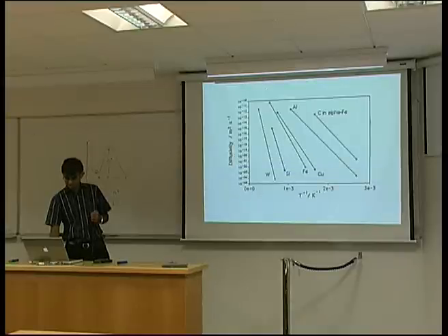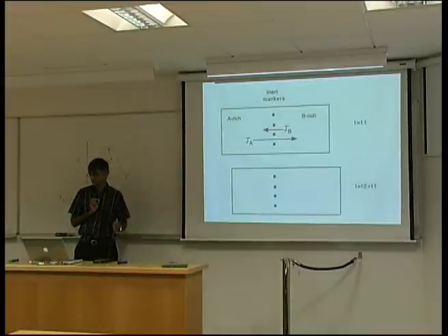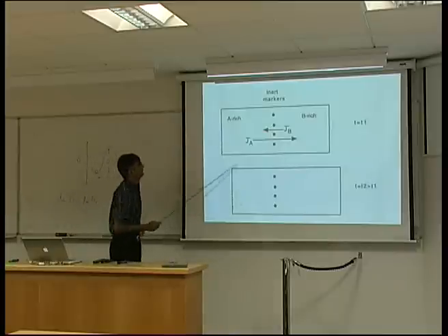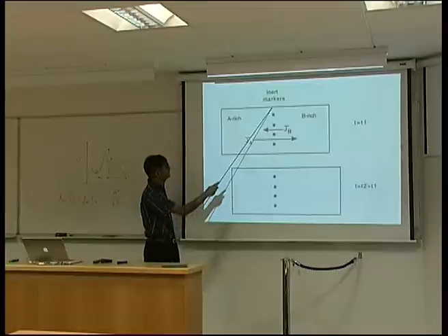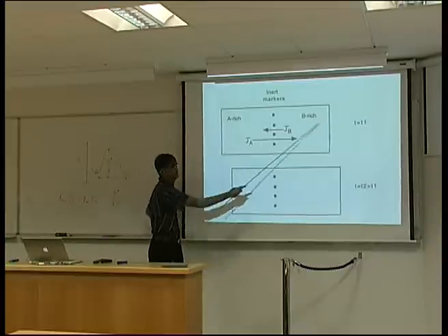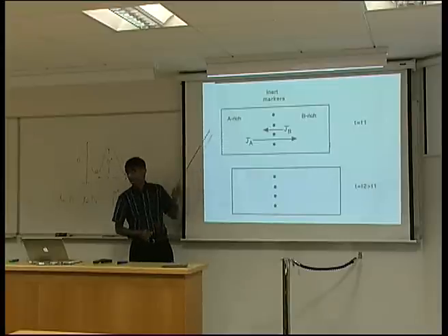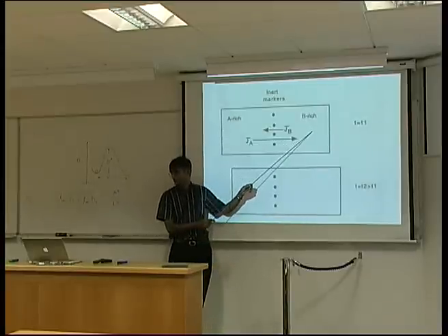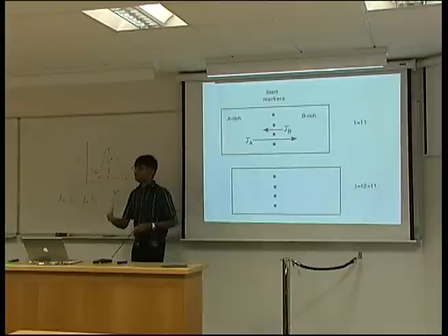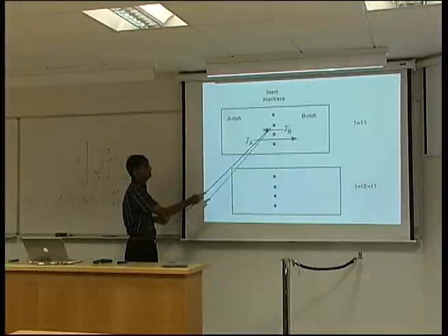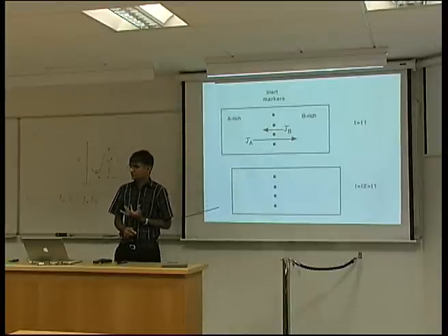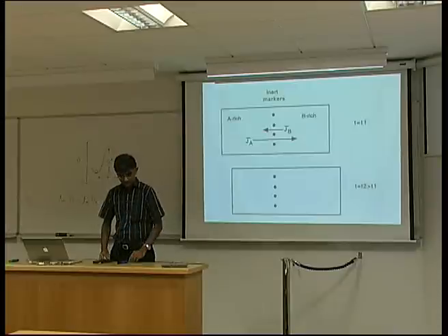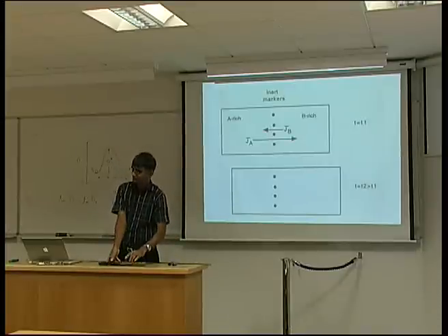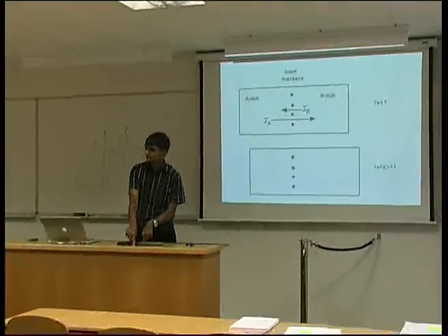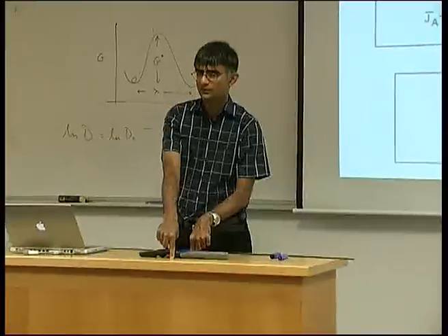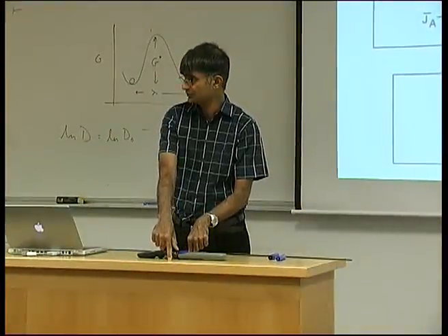Kirkendall and Smigelskas did a very, very neat experiment. And the experiment is as follows. We have a diffusion couple. That means we have joined together two pieces of material which have different chemical compositions. So this is rich in the A atoms on this side and rich in the B atoms on this side. And before you begin diffusion, you put inert markers here. That means markers which are not going to dissolve in the material, but are fixed. If this is my diffusion couple here, I put markers which are fixed to the bench. So I know exactly where the interface between the A-rich and the B-rich region is.